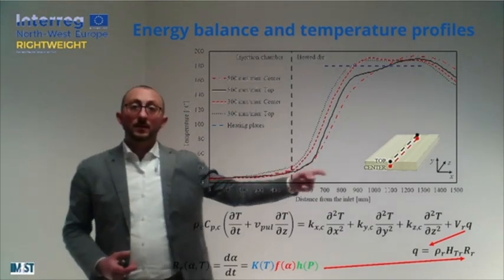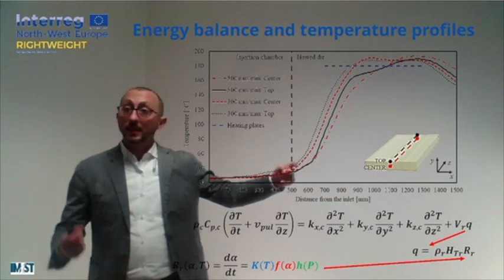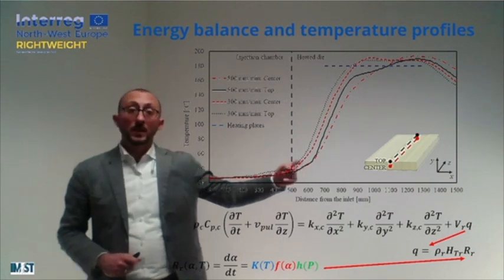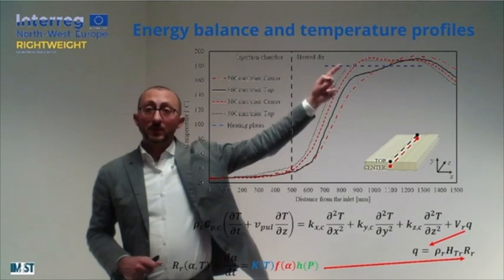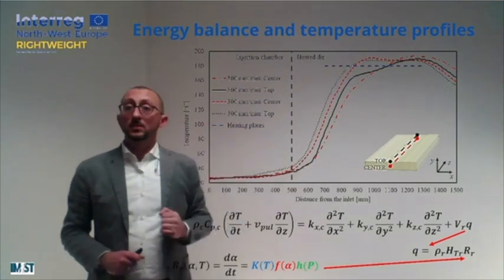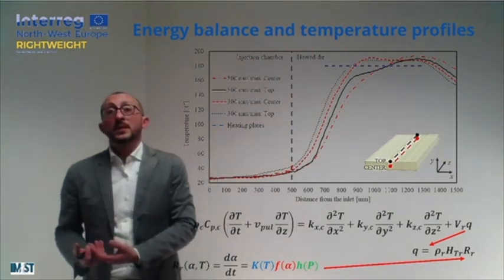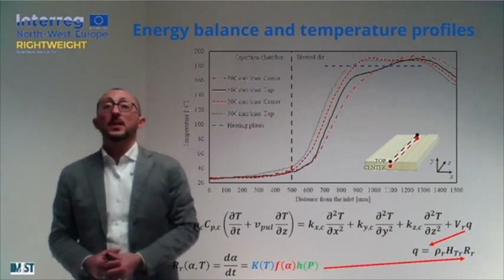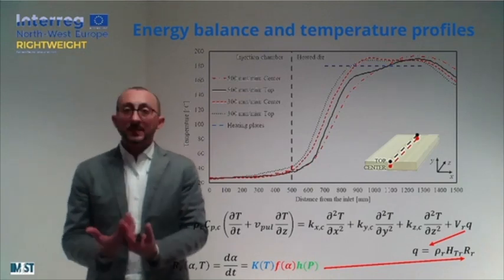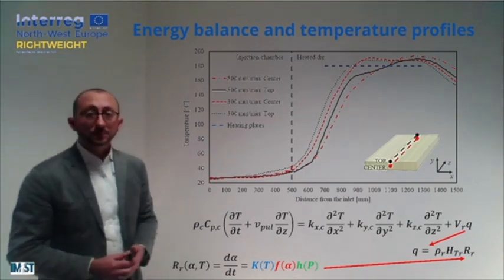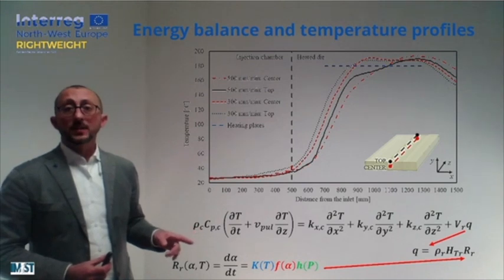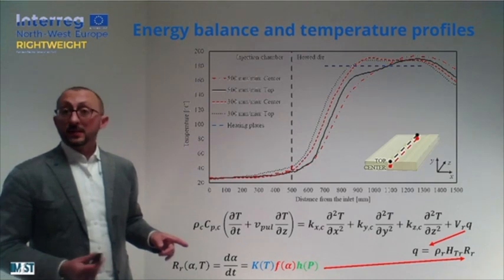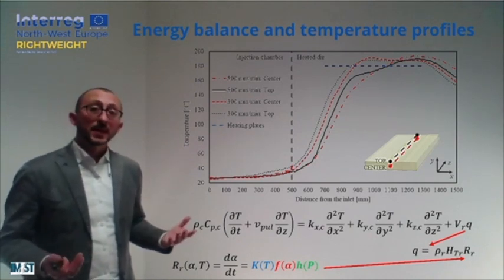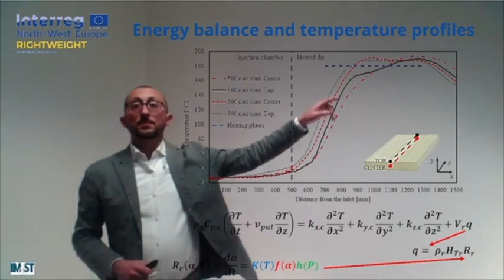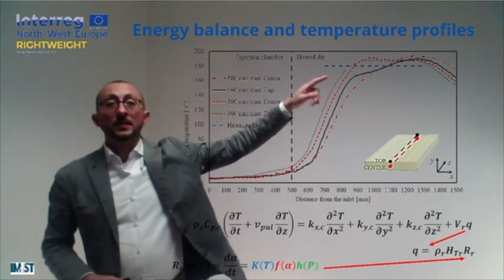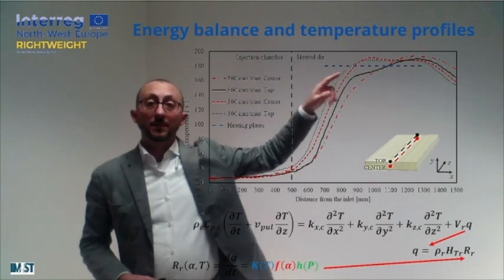But after the cooling channels have been crossed, the heat provided by the electrical heaters will promote the increase of temperatures in our material, on the surface first of all, and then in the center. This will provide the activation of the resin reaction. The resin reaction is typically exothermic in nature, meaning that further heat will be generated by the material itself, and according to the energy balance that is written here for our traveling material, combined with some other equations that are explaining how the material is reacting and how heat is generated, at some point inside our die the processing material temperature will overcome the temperature of our heaters.